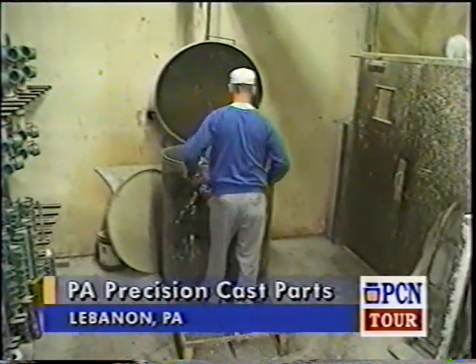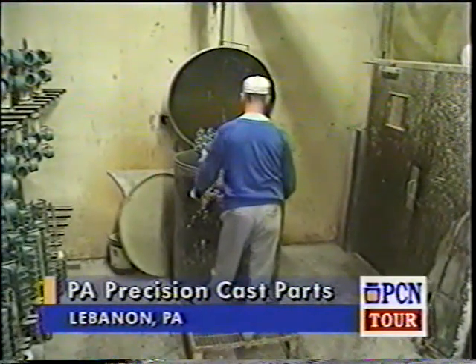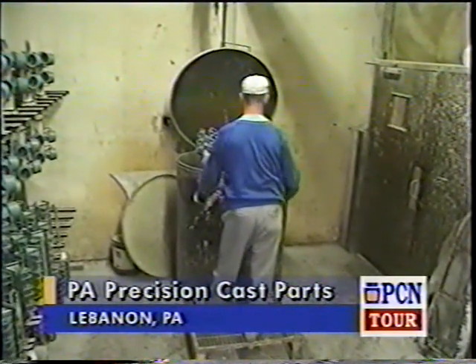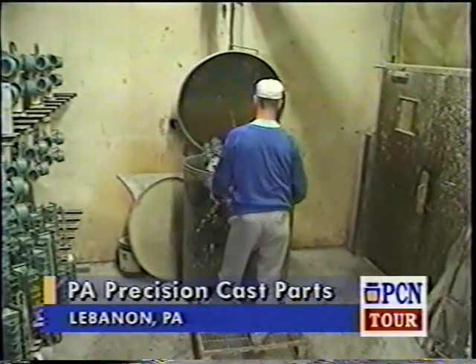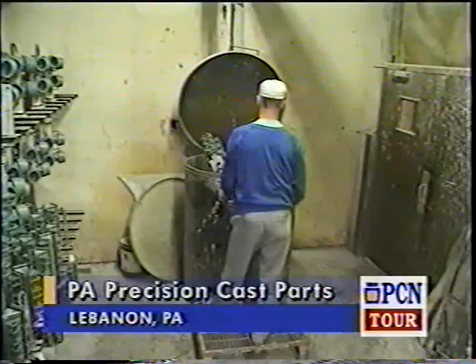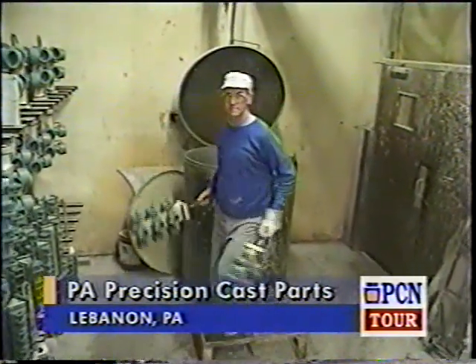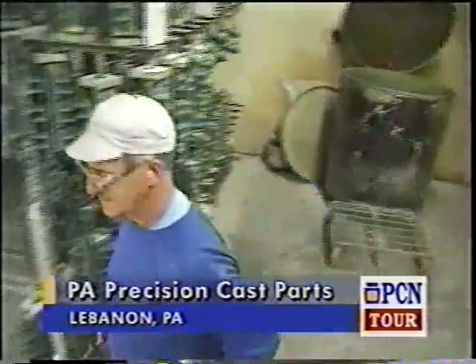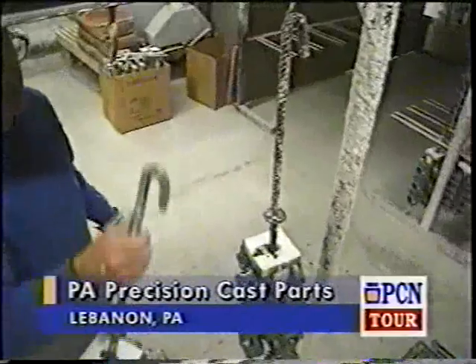Before the molds can get dipped, they need to be pre-washed. They're put in a special pattern wash for about 15 seconds and gently agitated, which removes the mold release from the injection process as well as any oils or films that were picked up in the handling of the part prior to the dipping operation. They're allowed to dry for a minute or two, then the dipping process can begin.